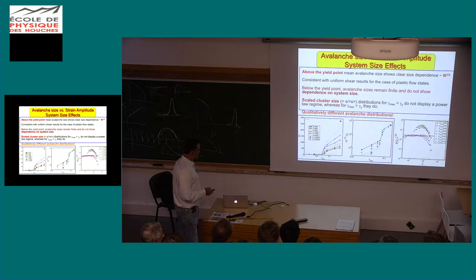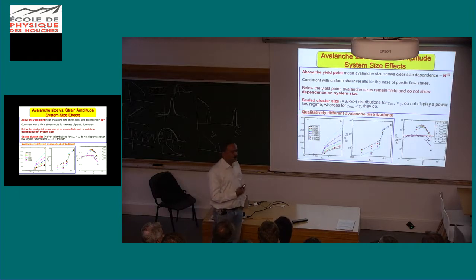But based on the expectation that avalanches scale as n to the 1/3 in the steady state regime, we scale our data to that expectation, and we find that indeed all the different system sizes in the above threshold regime fall on that predicted scaling, whereas at smaller amplitudes you see that in fact the avalanches are finite, and dividing by n to the 1/3 takes them to lower and lower values as you go to larger system sizes.